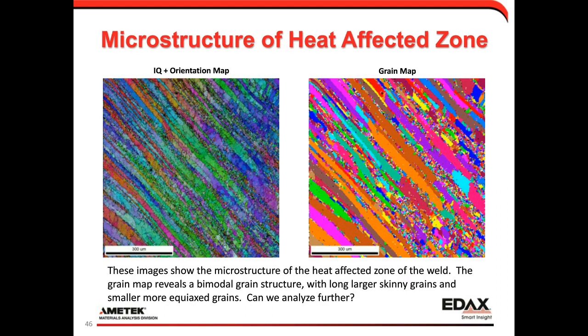So this is just an extraction right at the heat affected zone here. On the left we have the base material and the grains that are bending into the weld. On the right is the grain map, so we can see there are some long grains, and then some smaller, more equiaxed grains in the structure. And so the question is, how can we analyze this particular area of the weld a little bit more in detail?